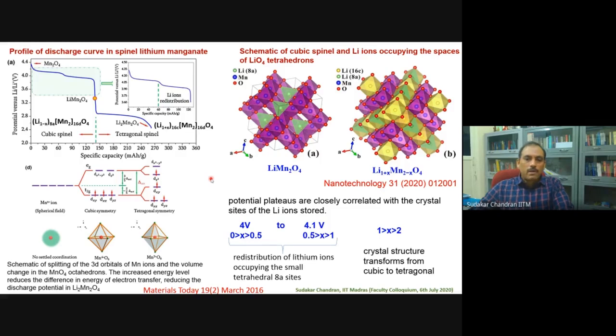There is a site-dependent voltage that a material can give. For example, in this region, it gives around 4 volt. There itself, you have two different kinds of lithium distribution, and therefore the voltage slightly changes. And the other one, if you try to put the second lithium, the voltage is totally different.